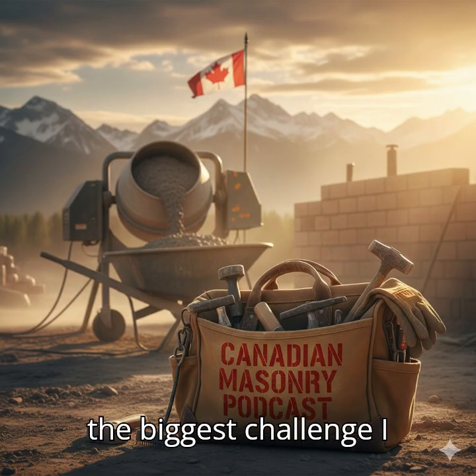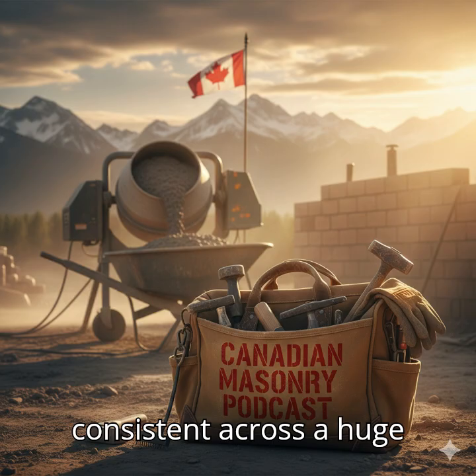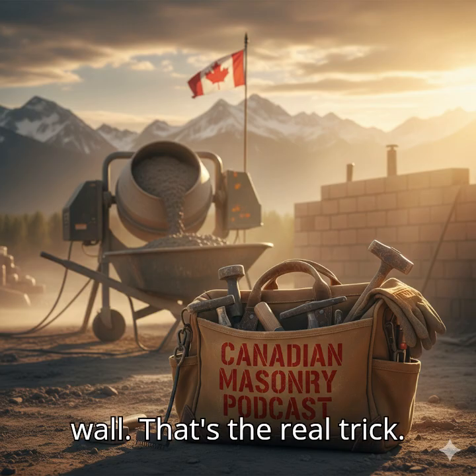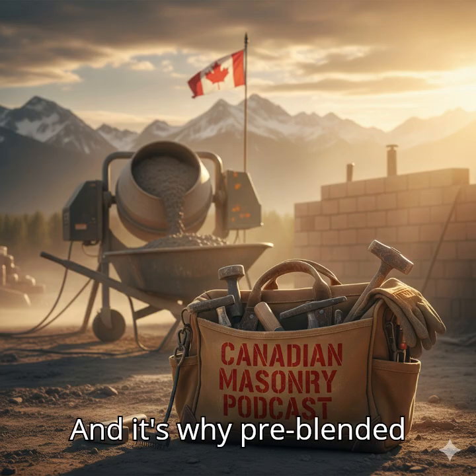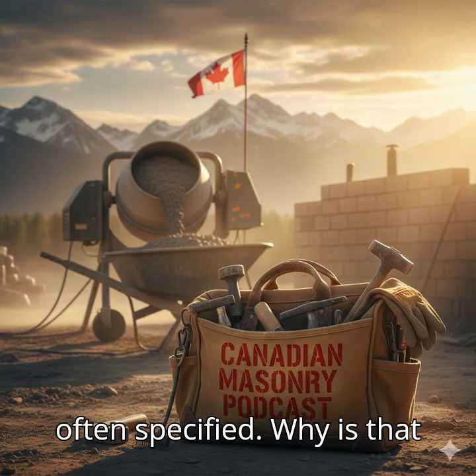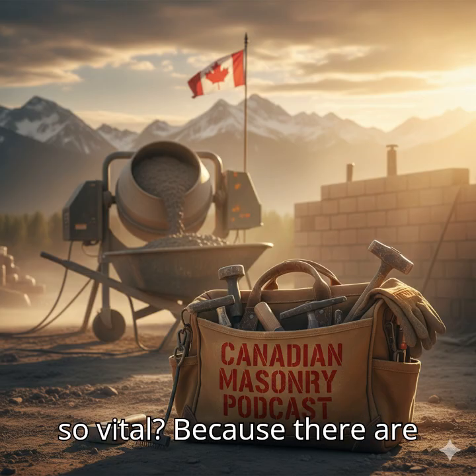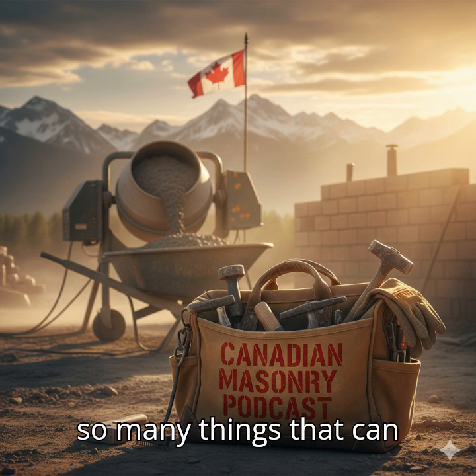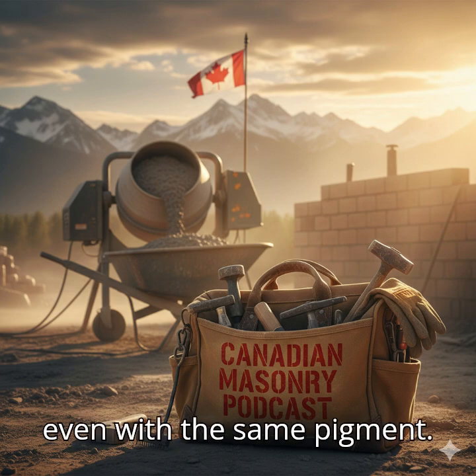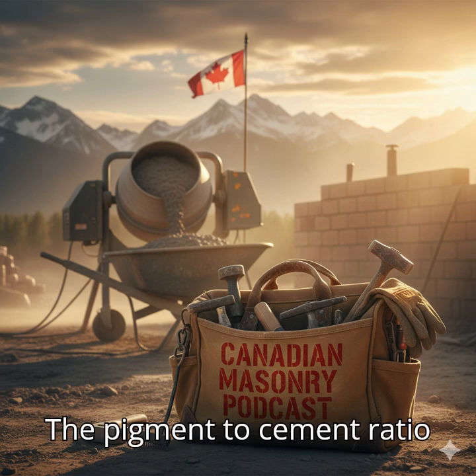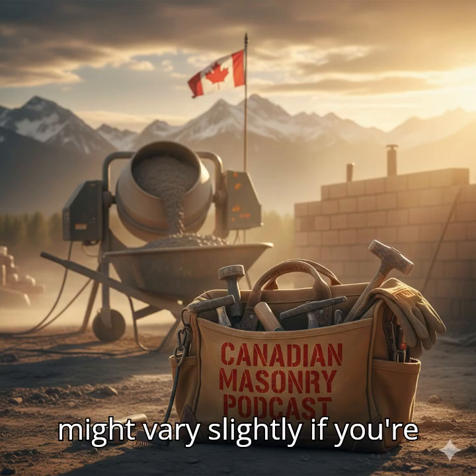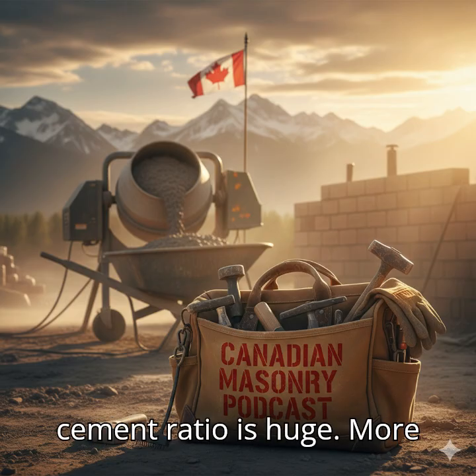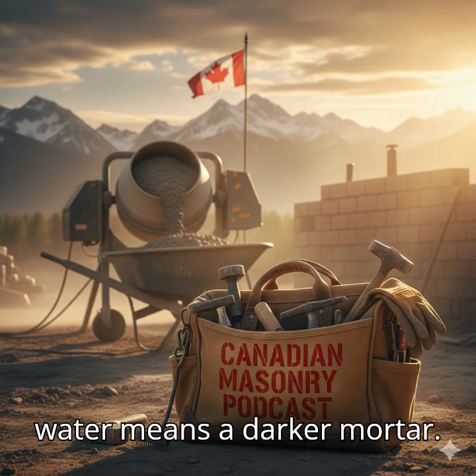But the biggest challenge, I imagine, is keeping that color consistent across a huge wall. That's the real trick. And it's why pre-blended, factory-mixed mortar is so often specified. Why is that so vital? Because there are so many things that can change the color on site, even with the same pigment. The pigment-to-cement ratio might vary slightly if you're mixing by hand. The water-cement ratio is huge. More water means a darker mortar.